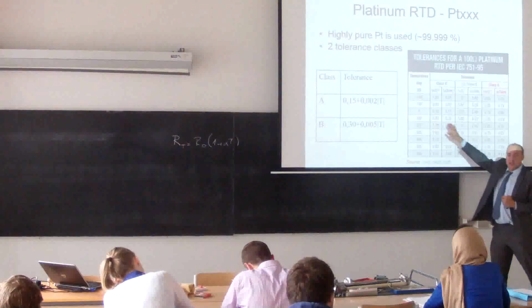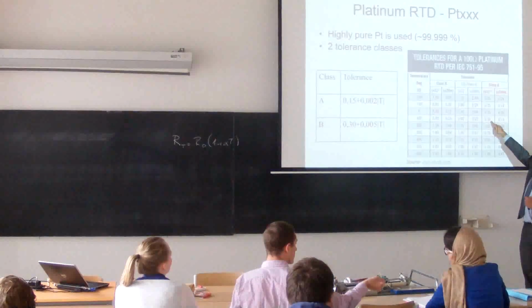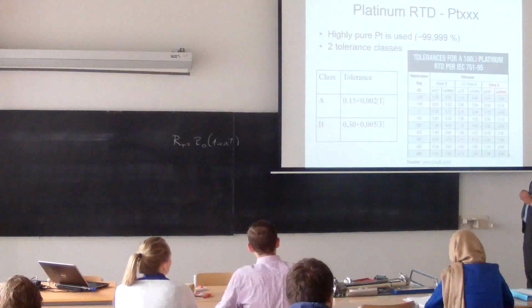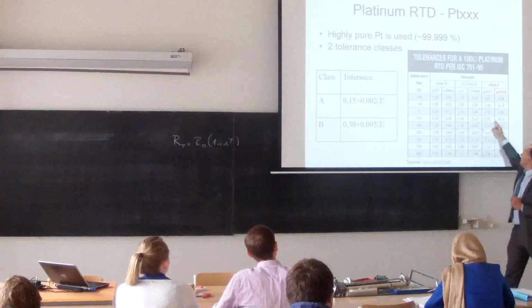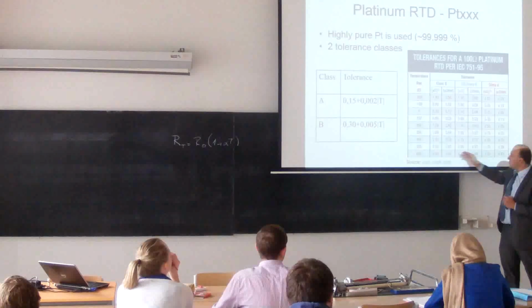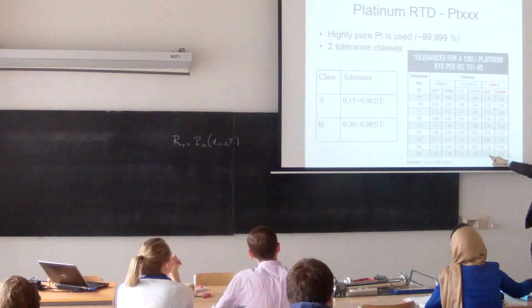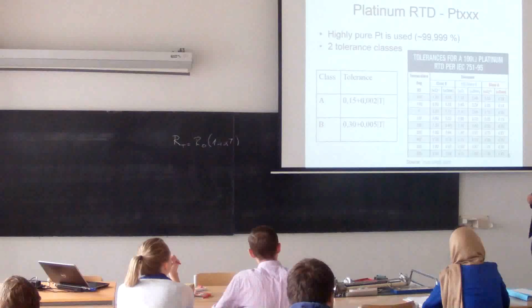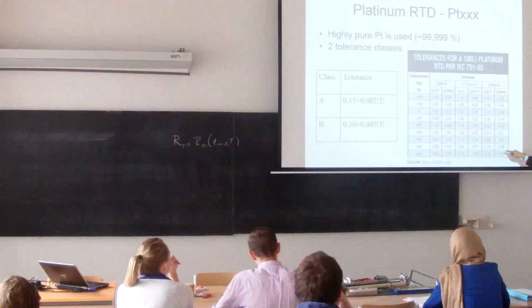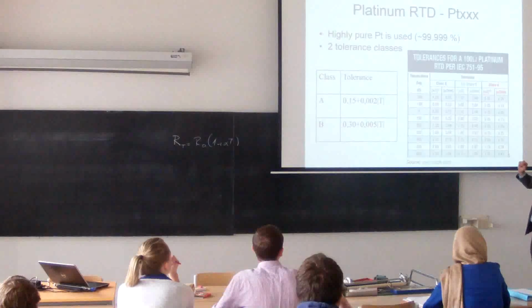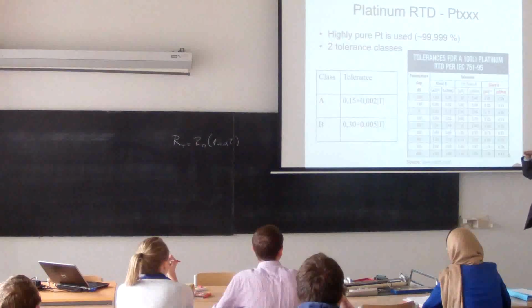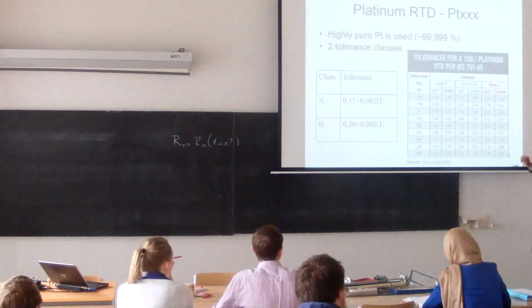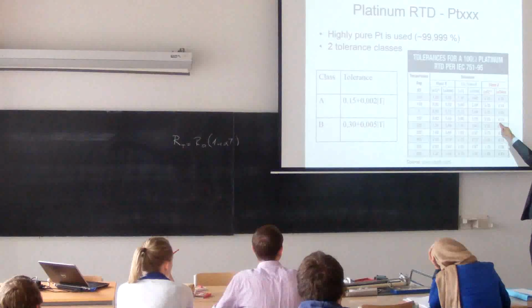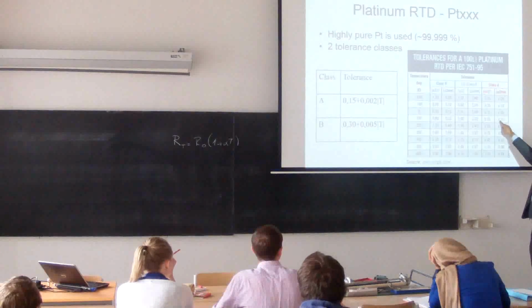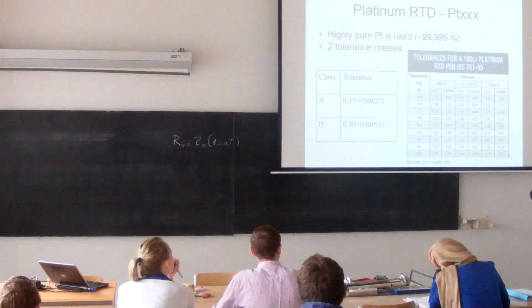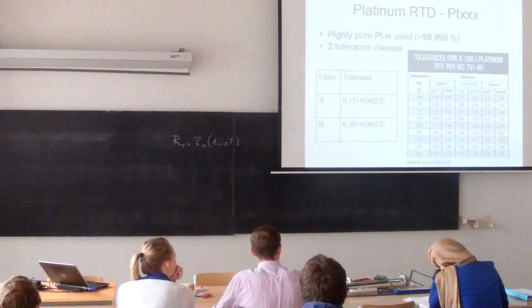For 100 centigrade, this accuracy class gives you something about 0.35 centigrade. So it's very precise. Even if you have 600 centigrade, then for class A accuracy, you have plus minus 1.35 centigrade. In ohms, it gives you a very small value compared to the basic value of 100 ohms. If you have 100 centigrade, then you have plus minus 0.13 ohms. So again, you need to measure the electric resistance very precisely.